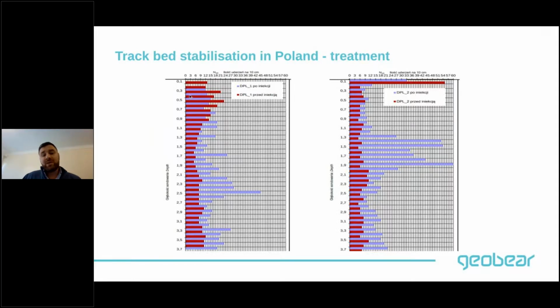And the blue bars represent the dynamic probing blow count after the injections. And you can see in both samples there's a significant increase of blow count after the injections, reaching almost 6 times increase, and that would obviously translate into higher shear strength and higher track stiffness there.